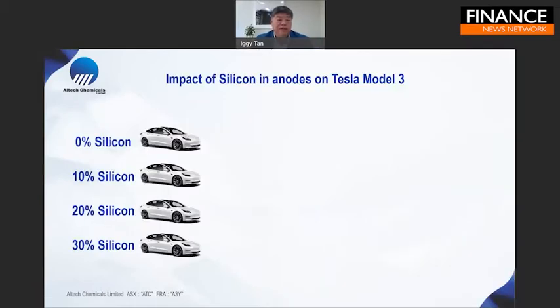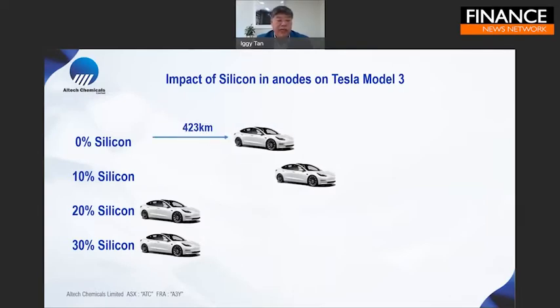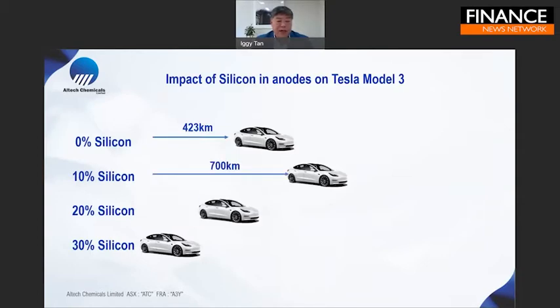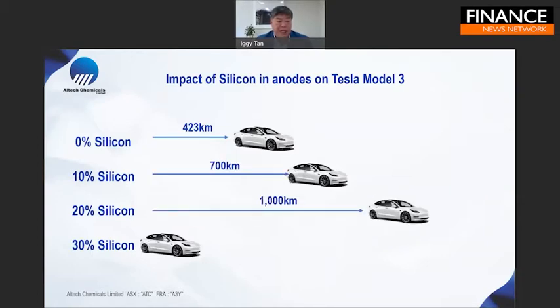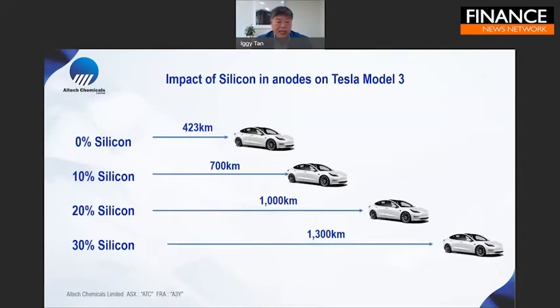Now, how does that transfer to a vehicle? Well, if you look at a Model 3 in a Tesla, it does 423 kilometers. By adding 10% silicon, it goes to 700 kilometers. 20% silicon goes to 1,000 kilometers on one single charge. And at 30% silicon, 1,300 kilometers on a single charge. Now, you can see the dramatic improvement in battery performance just by adding a small amount of silicon. And obviously for the car manufacturer, they'll keep the range the same, but reduce the cost of the battery.